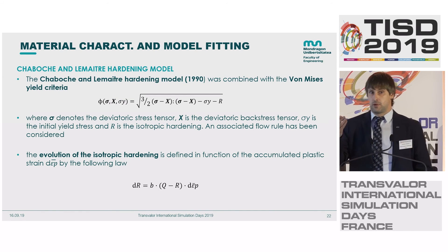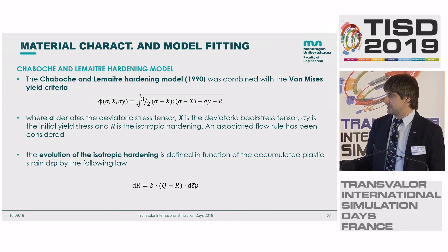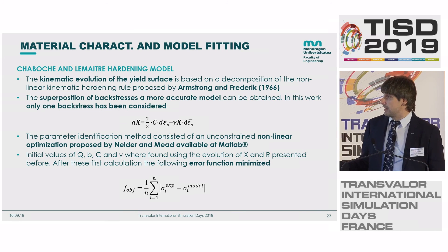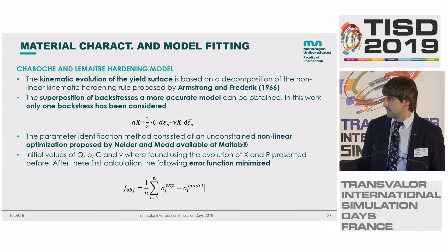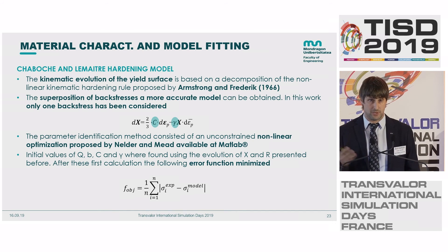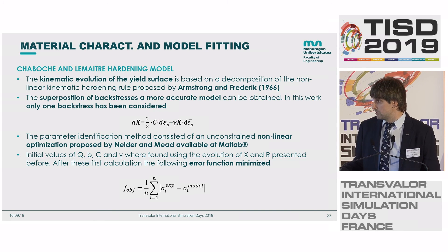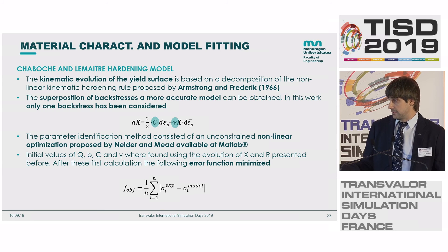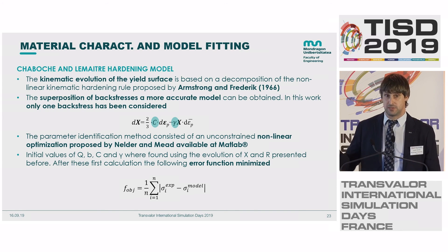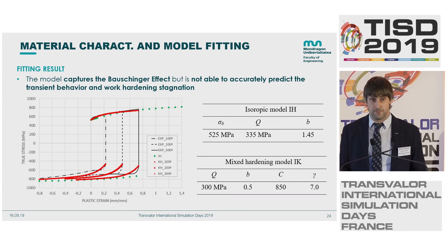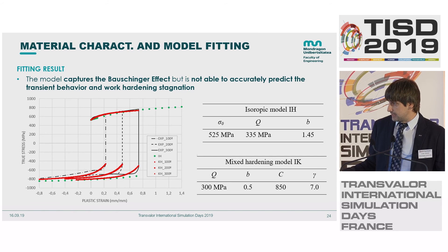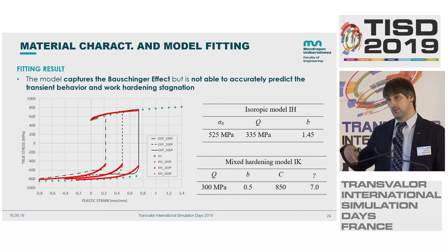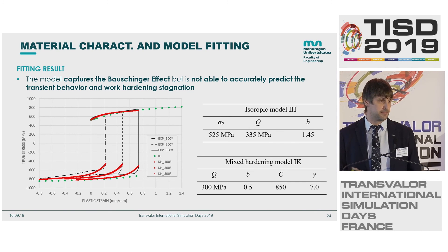Together with Patrice, we coded this in Forge using Voce's law for isotropic hardening with parameters b and Q, and the Armstrong-Frederick model with parameters C and Gamma — also known as the Chaboche-Lemaître model. We used an initial guess from the data and then a classical minimization algorithm to fit the parameters. The fitting shows some errors, but a second backstress term would improve accuracy and is likely the next step.